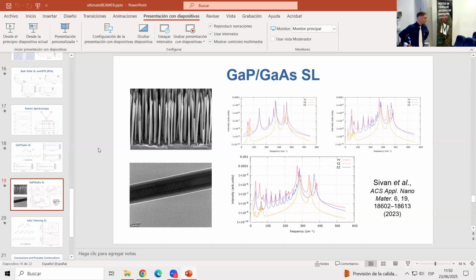So first I would like to ask, how do you link the strength of phonon peaks with the homogeneity of the force field? Because as a first intuition, I would link it to some electronic responsivity rather than to the homogeneity of the force field, meaning it's not a given that if you change the composition, the peaks increase in intensity. I would like you to comment on that. And the second thing is, isn't it intuitive that a twin boundary scatters phonons less than a compositional boundary, to your understanding?